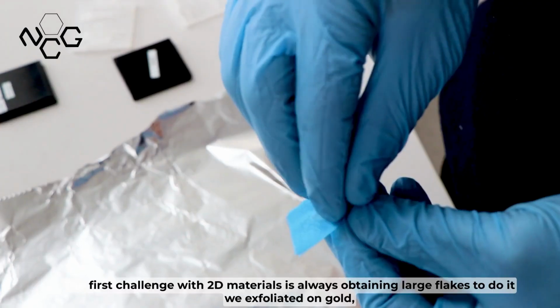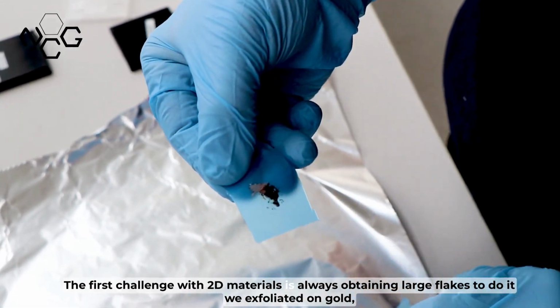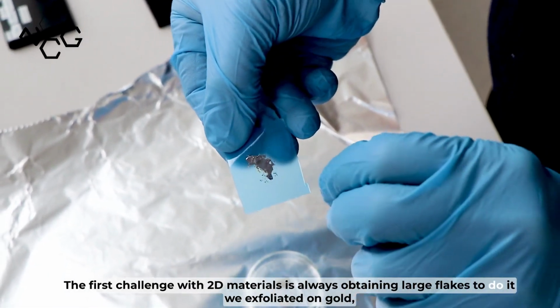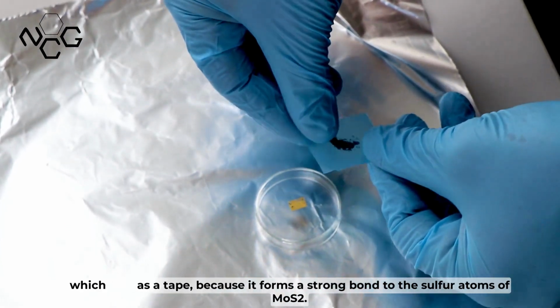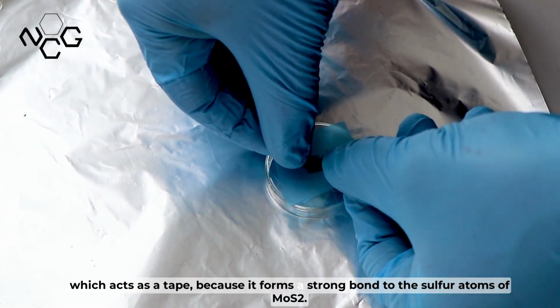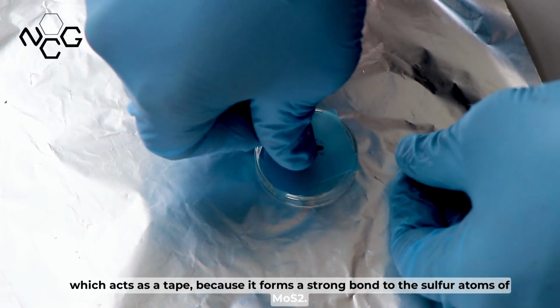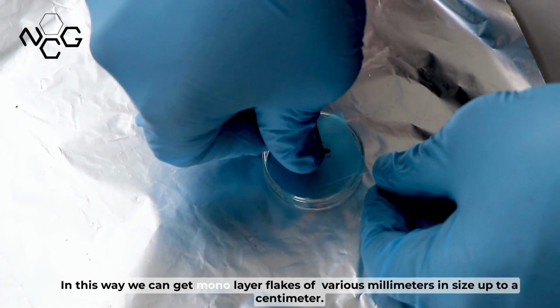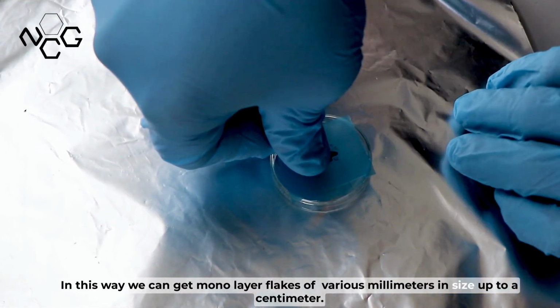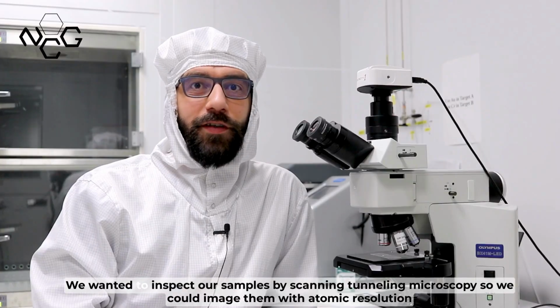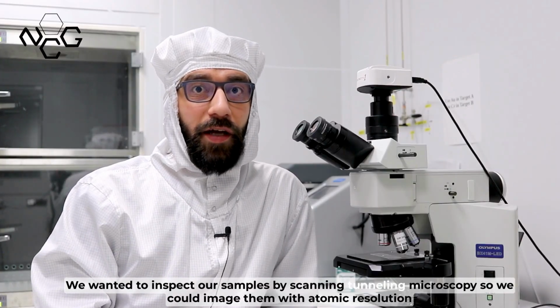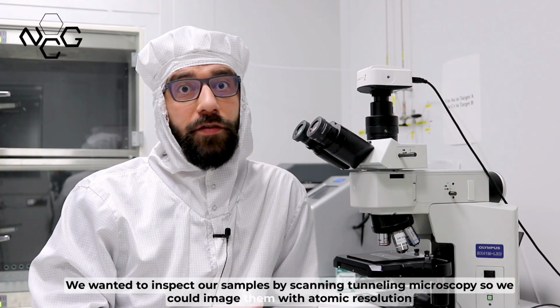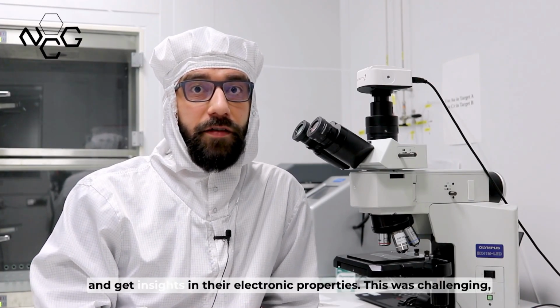low bandgap. The first challenge with 2D materials is always obtaining large flakes. To do it, we exfoliated on gold, which acts as a tape because it forms a strong bond to the sulfur atoms of MoS2. In this way, we can get monolayer flakes of various millimeters in size, up to a centimeter. We then wanted to inspect our samples by scanning tunneling microscopy, so we could image them with atomic resolution and get insights into their electronic properties.